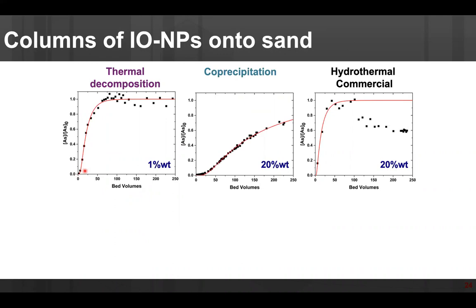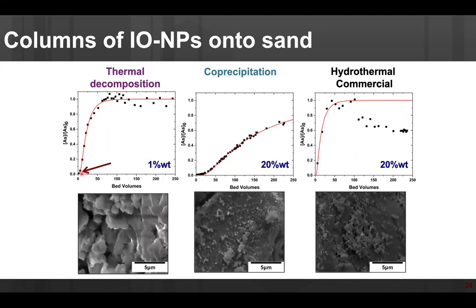Instead of going to a 20%, because this takes a lot of material and time, I did a 1%. And if we look in the tail, we can see that it's not a good column. Well, maybe co-precipitation is, but I wanted to look at how this looks in the sand, because the beads are very spherical, very smooth, very homogeneous. Sand is also smooth, but still you have different areas, right? And this roughness that you see is coming from the nanoparticles. You cannot really see the nanoparticles in here, but you can see how the contrast changes.